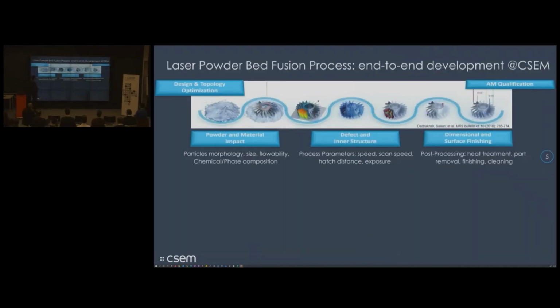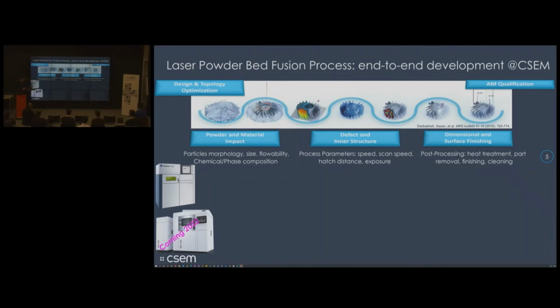For the laser powder bed fusion process at CSEM, we handle what we call end-to-end development. We really start with design and topology optimization, for example. Then we have capabilities to characterize and qualify the powder and how it can impact the manufacturing. We work on defect and microstructure investigation, and also post-processing. In laser powder bed fusion, the powder is the feedstock, and we use a laser to fuse the material locally in a layer-by-layer process. At CSEM, we have a TruPrint 1000 machine, and in 2022 we will have a new EOS machine capable of building larger structures, up to 250 millimeters in the long dimension.